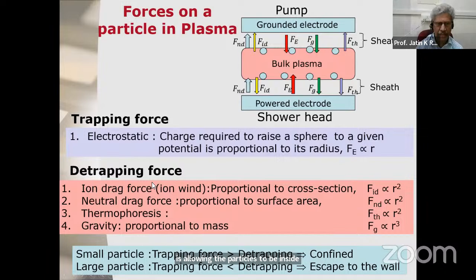This is trapping it. The de-trapping is that the particles can get out from the plasma zone and deposit on both sides. There is one called the ion drag force, by which a positive ion, for example, is coming there and pushing the negative particles, the dust particles, and dragging them along with it. This is called the ion drag force, which depends on the square of the size of the particle.